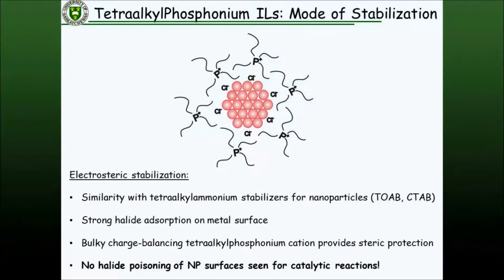We tried to understand why this was, and we played with a whole bunch of different anions. It turned out the halides are the best. And you think about the halides, they actually adsorb very, very strongly to metal surfaces, chloride, bromide in particular. Iodide does as well, but then you have some iodide-iodine chemistry that you would like to avoid. But essentially a halide adsorption, a co-adsorption of the cation with that halide.